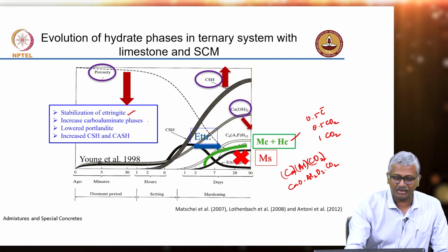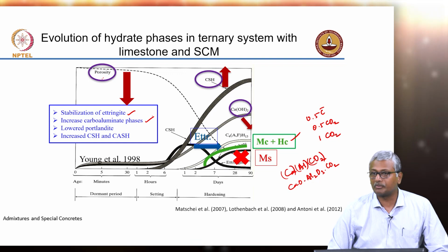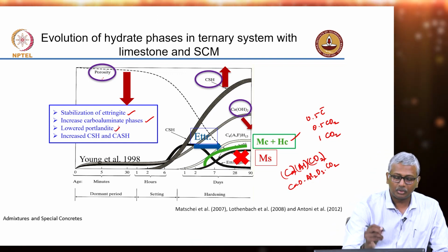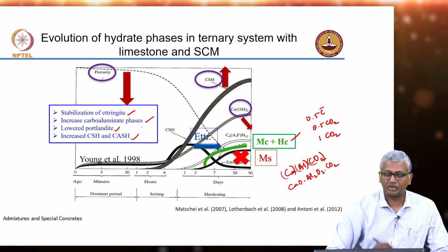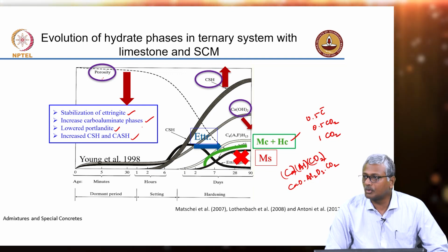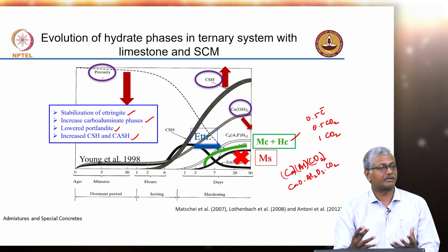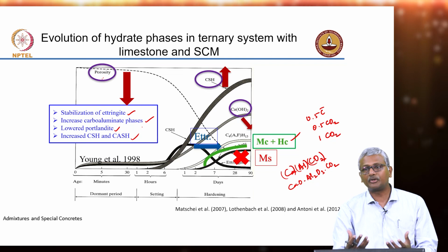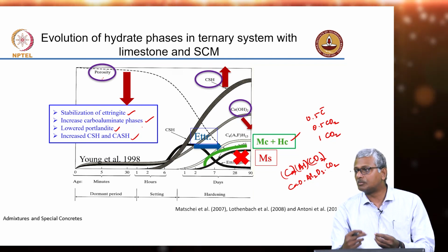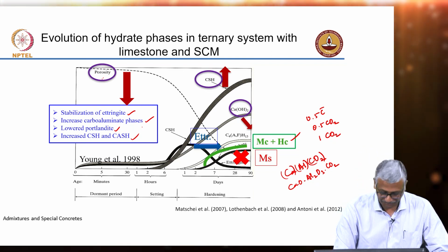So, these are the main aspects that you see: stabilization of ettringite, increased carbo aluminate phases, lowered portlandite content, and increased calcium alumino silicate hydrate. So, overall your volume filling ability of the hydration products gets better, and you have less interconnected porosity available in your system.